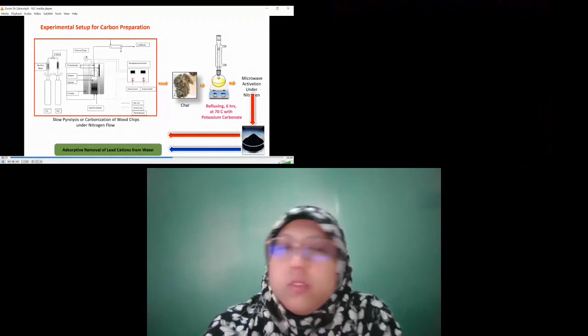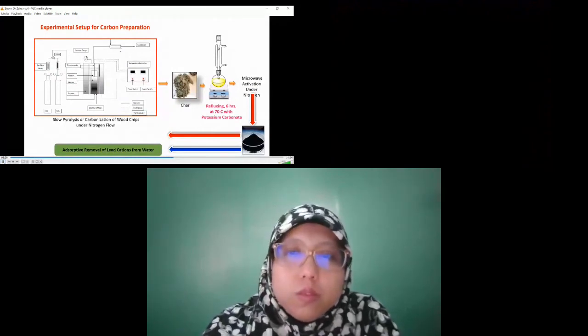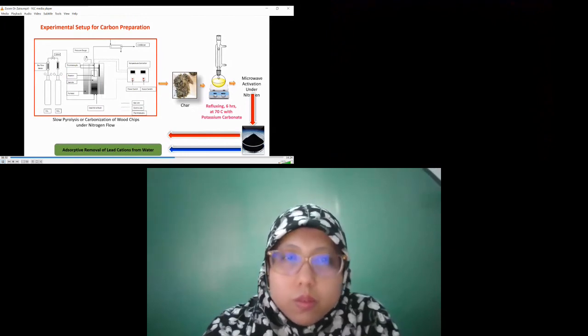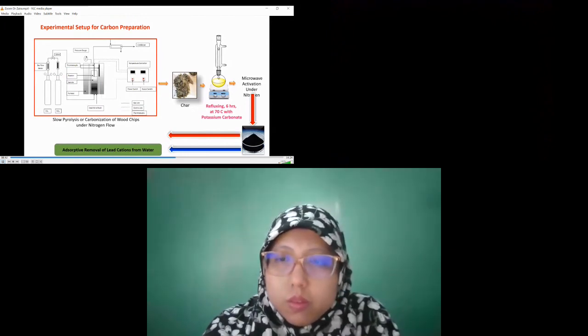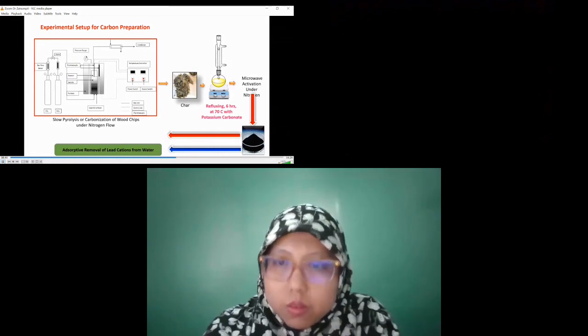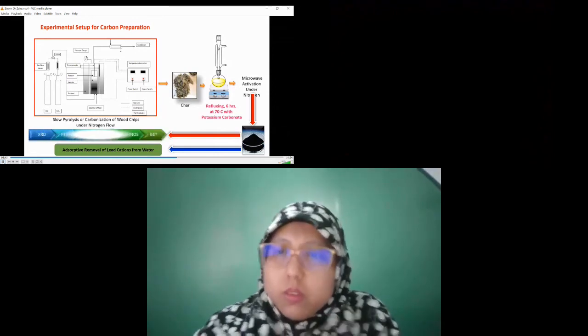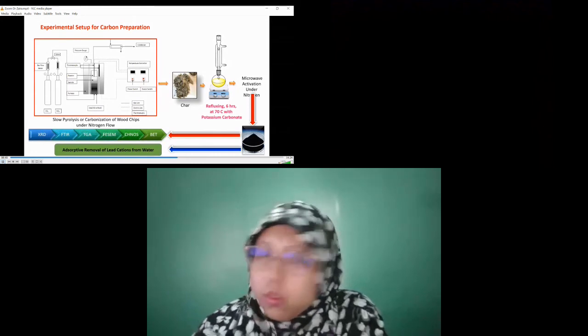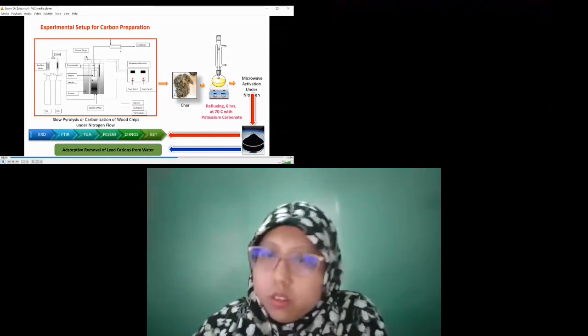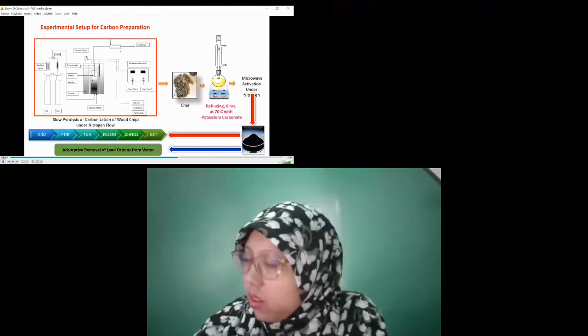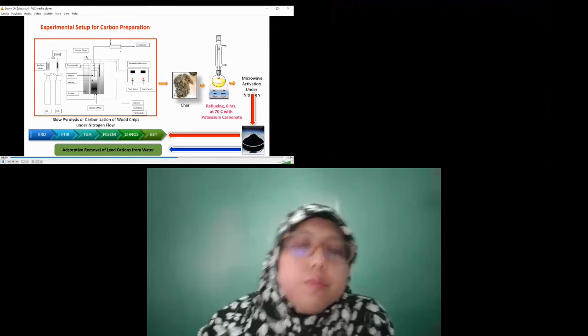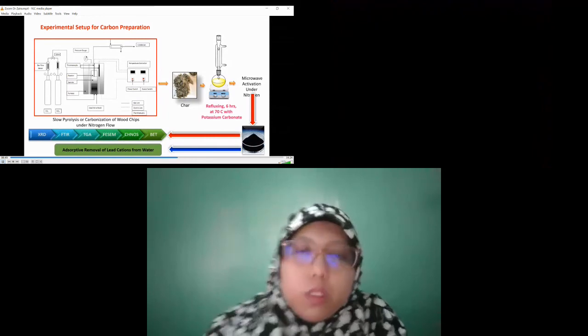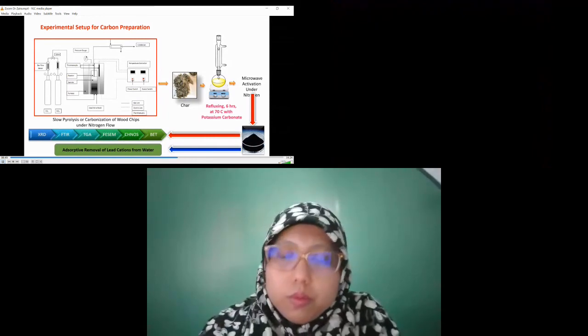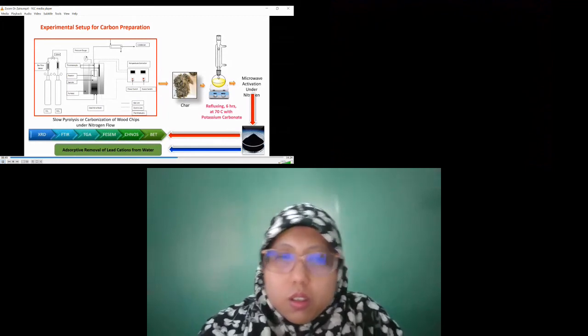After this fixed bed pyrolysis process, we will get the char, which we will mix with potassium carbonate and reflux for 4 hours at 70 degrees centigrade. We will get the impregnated char. This impregnated char we will put into the microwave to activate it and get our activated carbon. Both char and activated carbon we will characterize and use for lead cation removal. For the pyrolysis process, as we said earlier, we are interested in slow pyrolysis, when the temperature increases slowly in the reactor, at 5 degrees centigrade per minute.